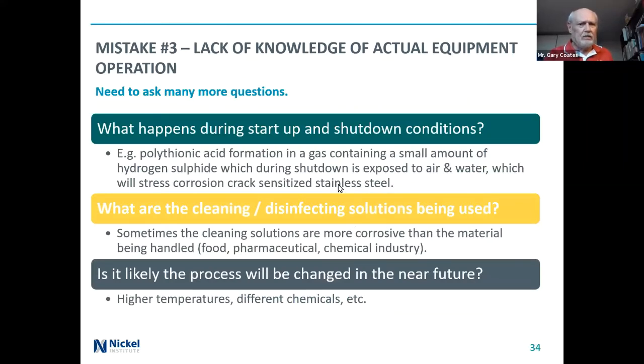So really we need to ask more questions. What happens during startup and shutdown conditions? Those of you who work in oil and gas know about polythionic stress corrosion cracking. You can get that forming during shutdowns where hydrogen sulfide is in a gas. There's oxygen and moisture in the gas. It will cause stress corrosion cracking of sensitized stainless steel. So we're well aware of that as corrosion people. Not everybody is aware of that.